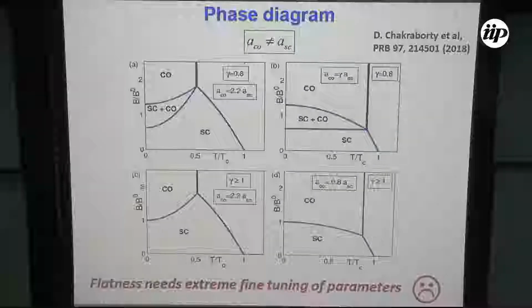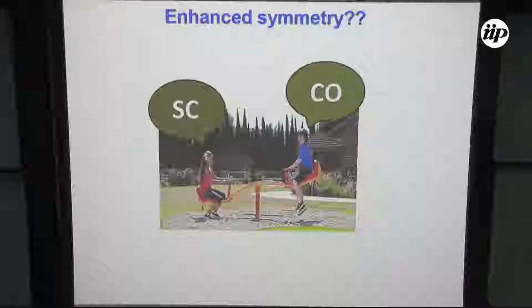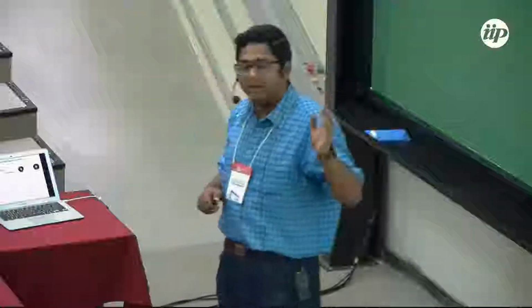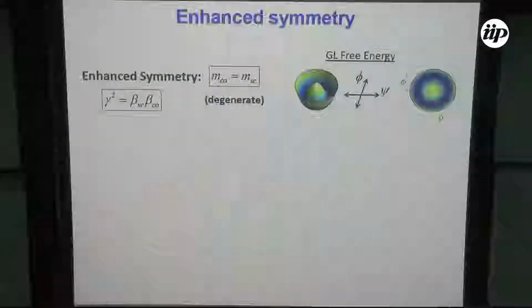So let's see whether we can improve with an enhanced symmetry picture. To understand this enhanced symmetry, let me go back to the Landau-Ginzburg free energy. So if we take the two masses to be equal, and set all the parameters such that the two energies are exactly the same, then plot the free energy in the superconducting charge order plane. If we plot it, we will see that it shows a Mexican hat-like potential with equal energy contours being plotted here. So if we go on one equal energy contour, we can have different values of phi and psi, but the free energy will remain the same.